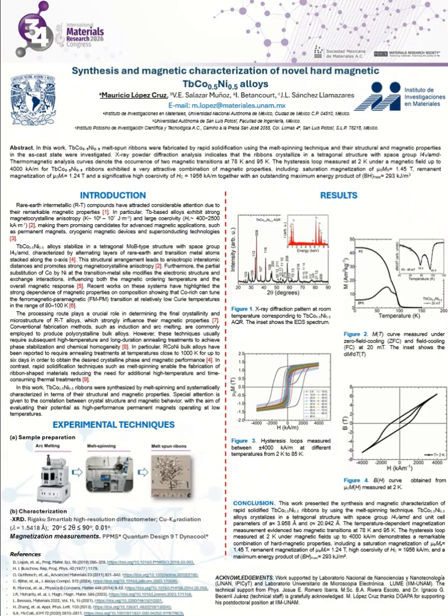Figure 3 shows the hysteresis loop for the studied samples. As can be seen, typical hard magnetic behavior is observed over the entire temperature range below the ferromagnetic-paramagnetic transition. At 2 Kelvin, under an applied magnetic field up to 4000 kA/meter, the sample exhibits a remarkably high coercivity of almost 2000 kA/meter. In addition, these ribbons display attractive magnetic properties, including a saturation magnetization of 1.45 teslas